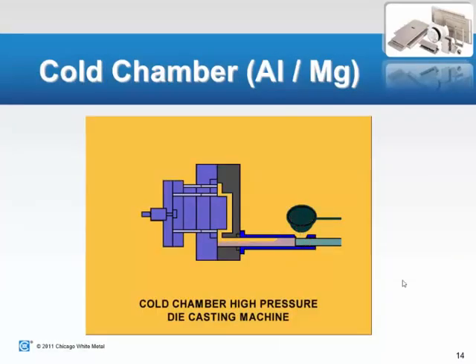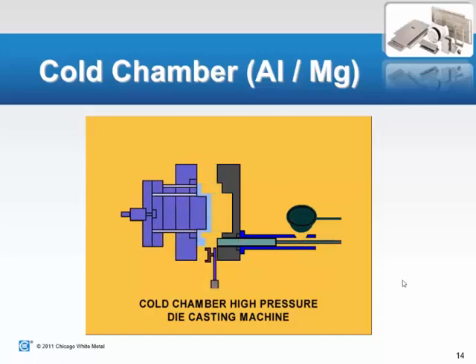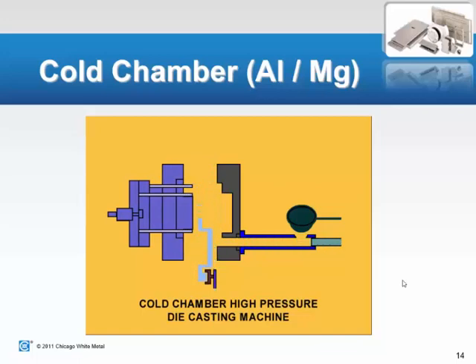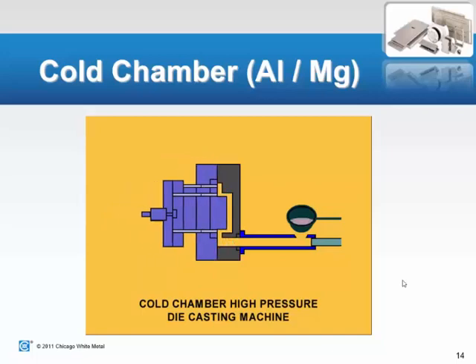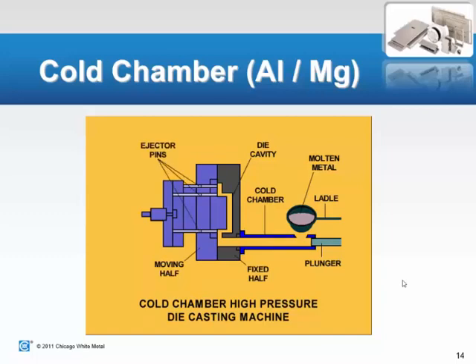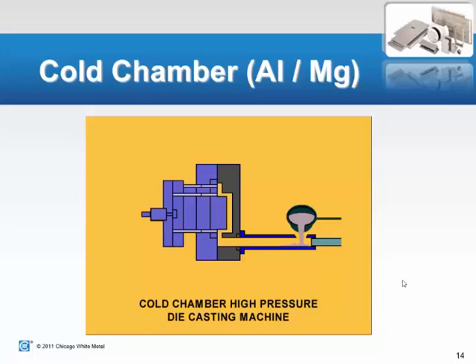So here you can see an example, or a pictorial, of the cold chamber process. Conceptually, it's pretty easy. You have an amount of, in this case, aluminum or magnesium for a cold chamber outside the machine. A ladle goes in and scoops a given amount of metal, pours it into the plunger area, and then it is shoved into the die at very high pressure.